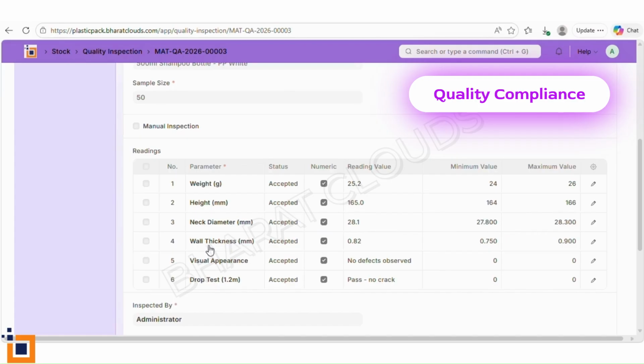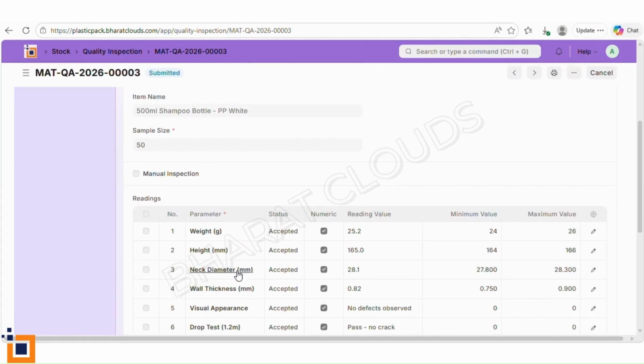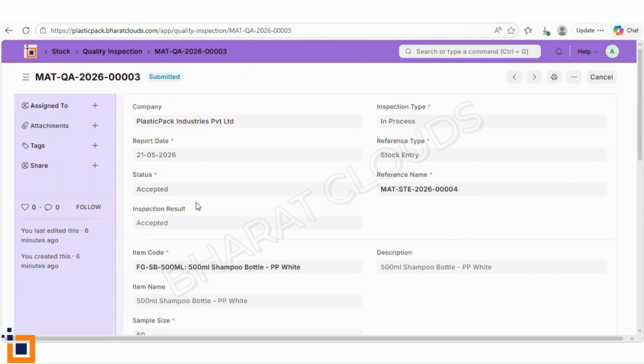Pass. This one matters because the cap has to fit perfectly. Wall thickness, 0.82 mm, spec says 0.75 to 0.90. Pass. Visual appearance, no defects observed. Pass. Drop test from 1.2 meters, no crack. Pass. Status, accepted. These bottles are cleared for shipping. If any parameter had failed, the status would show rejected, and the system can block the delivery note until the quality issue is resolved. No shipping defective goods to the customer.